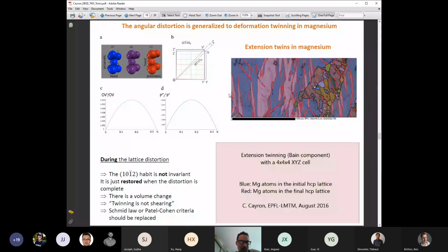when you change basal into prismatic and prismatic into basal plane by this type of twinning, and you look at this 1, 0, minus 1, 2 plane, that is supposed to be the invariant plane, the shear plane. If you look at the atoms inside this plane, you will realize that it cannot be fully invariant during the transformation. Some distances change, and then they come back to their initial length. It means that it's not fully invariant. It means that in the detail, in the mechanism itself, twinning cannot be a simple shearing. Well, here I had a movie also, but I cannot show you.